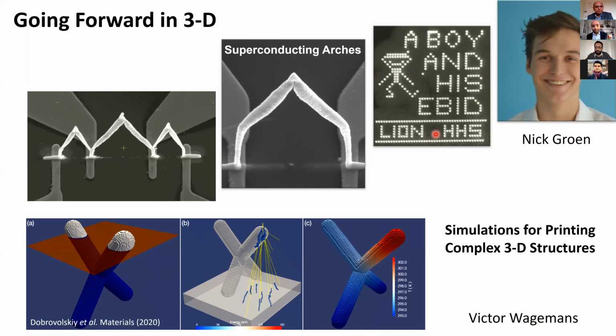I'll go back to the width in a second, but here's another advantage of disordered superconductors. They have a very small coherence length, in this case about 6 nanometers, which means that they have a very high critical field. And that is basically one of the main attractions here, why our friends in Tübingen are interested in this type of SQUID, because you could potentially go to 4 Tesla, 5 Tesla and operate the SQUID. You won't be able to do that with something like niobium or aluminium, where the critical fields are much smaller. This puts this type of SQUID on the same level as the ones made with YBCO or high temperature superconductors in terms of their robustness to magnetic fields.